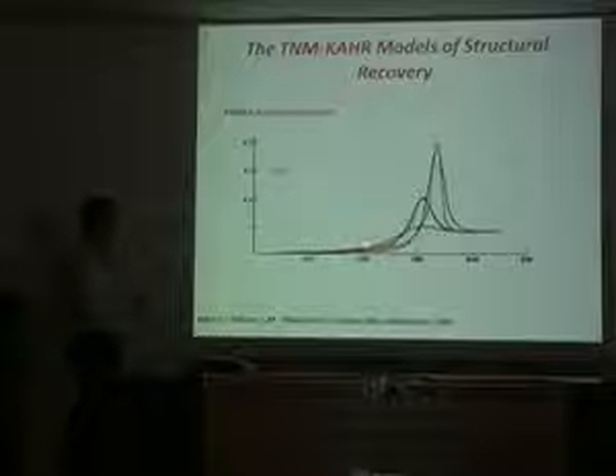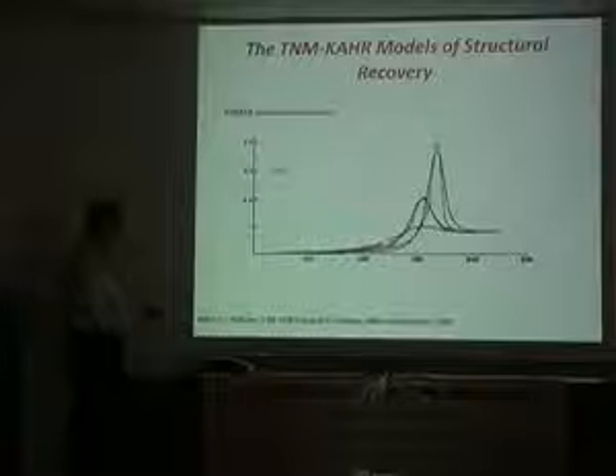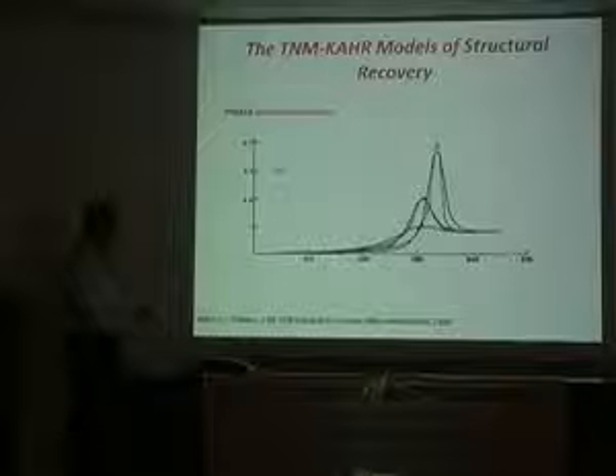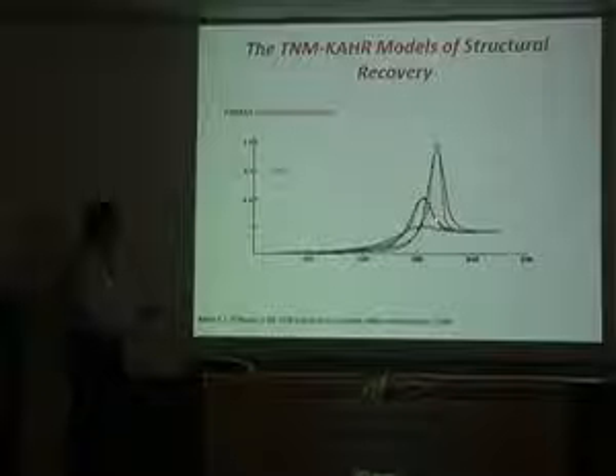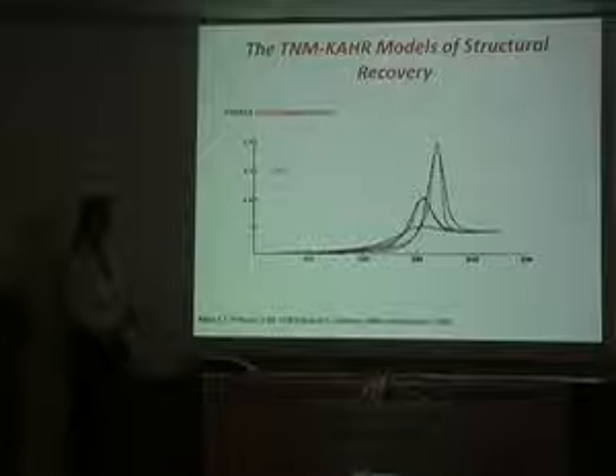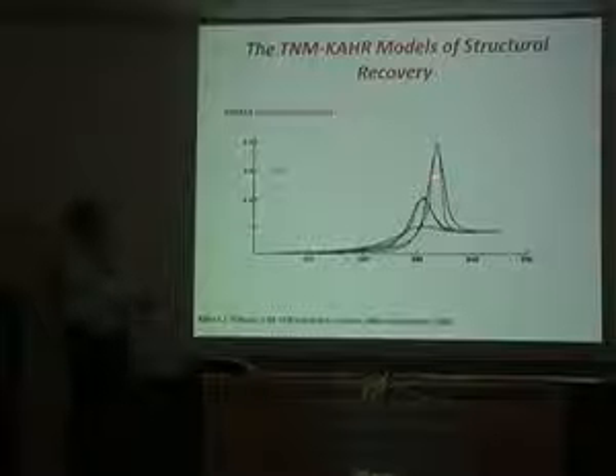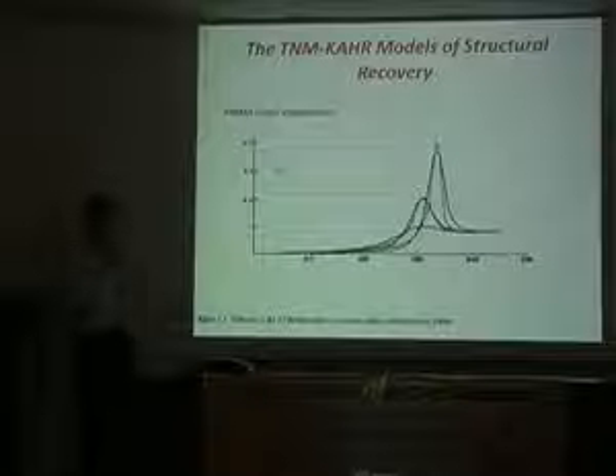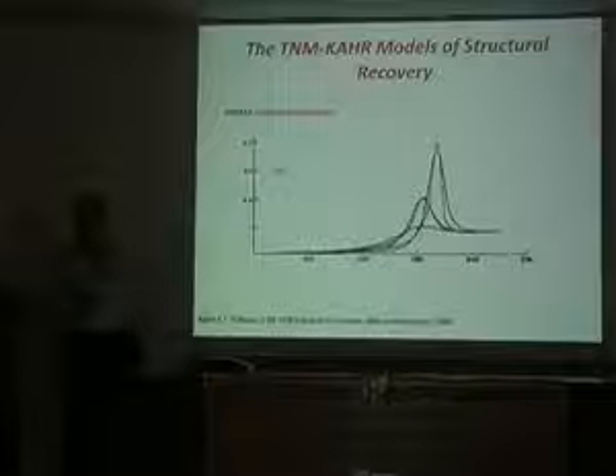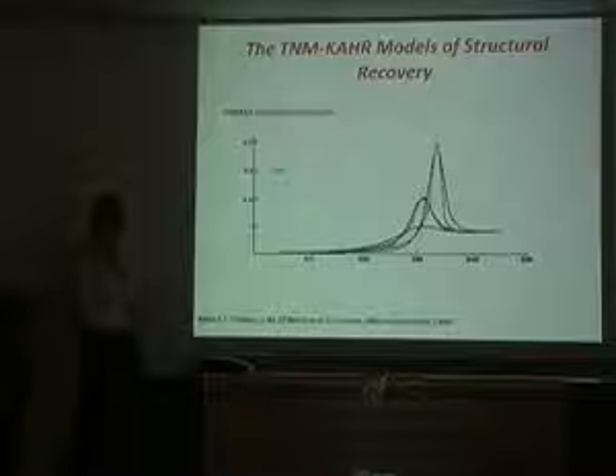So, here's the DSC experiment. This curve, the solid line here, is without any aging or structural recovery. This is one where there was structural recovery partially, and you can see you're starting to get this big excess enthalpy. And as you age it more, you get an even bigger peak. The dashed lines are the fits to the data. So the model captures that behavior pretty well. Not perfectly, though, so this is actually still a challenge. We don't fully understand what some of these deviations are.